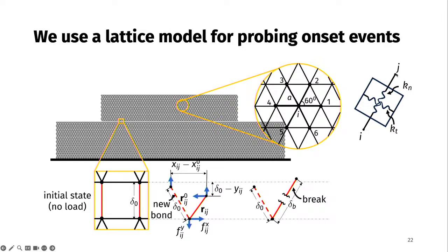Now at the interface we put, so these are all bulk bonds. At the interface we put interface bonds, right? And the interface bonds are different from the bulk bonds because they are single springs and they have an initial rest length. The value of the rest length doesn't matter because it just decides how close or how far away these bodies are, and that determines the time step for the computation and so on, but it's a minor detail.